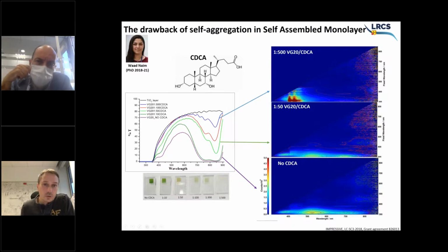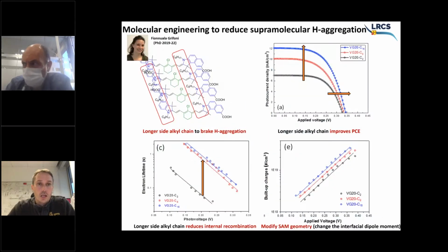And once you start to introduce this CDCA in the process of the sensitization, then you break the aggregates, and you turn out to have a photoanode which turns from green to something which is colorless. This also shows that when you have aggregation, you are quenching all the photophysical properties of the dye, and then you avoid injection, you avoid regeneration, and you simply decay the dye after excitation. So how important is the aggregation for the device performance?